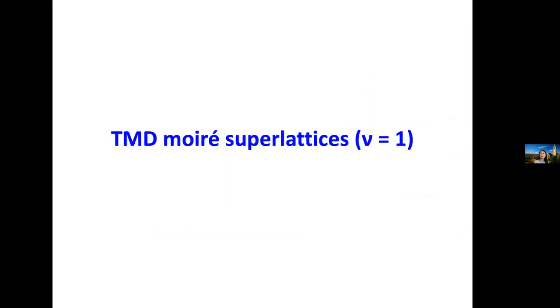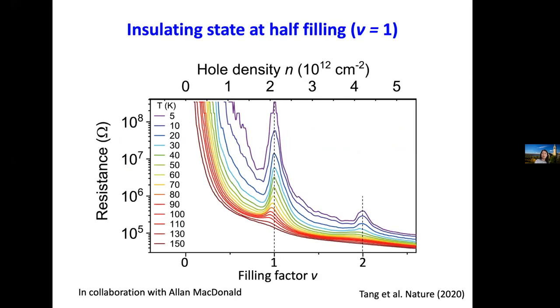Okay, so let me present the results at half filling of the Moire band, or the filling factor equal to 1 for the Moire superlattice. So 1 particle per lattice site. This is the temperature dependence of the in-plane resistance of the WS2/WSe2 Moire superlattice from 5 to 150 Kelvin. First, let's ignore the large resistance near 0 filling factor, and this comes from the non-ohmic contact resistance because of low density and a large band gap semiconductor.